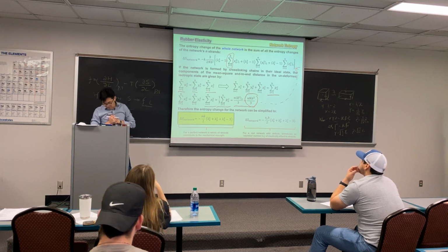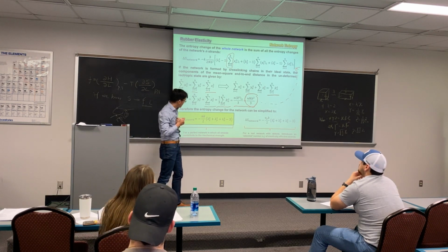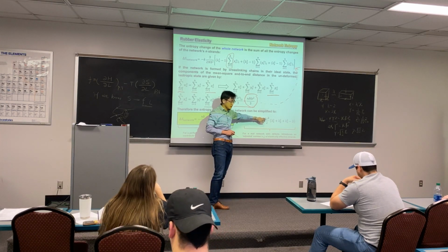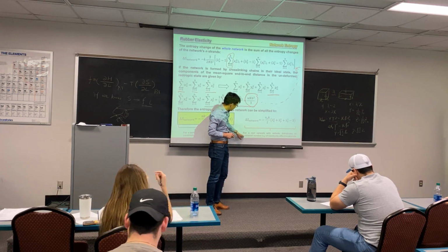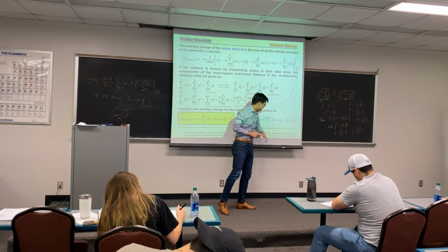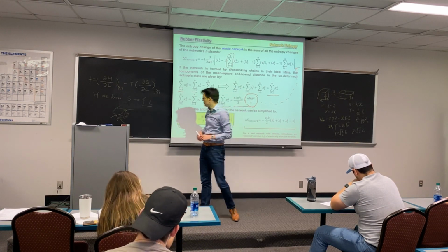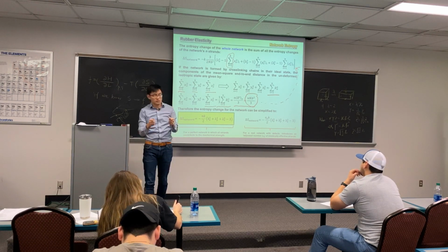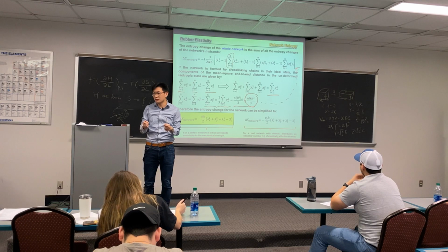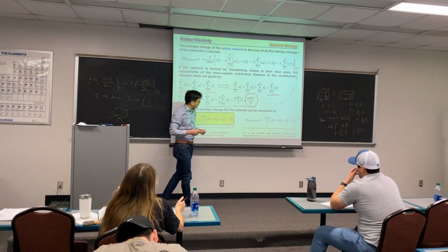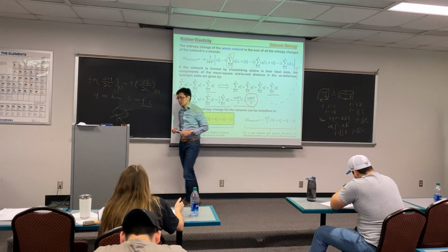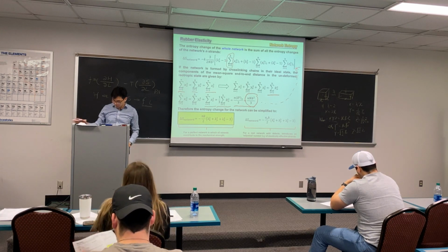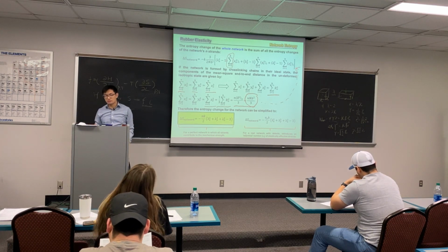you know exactly how much change there is in terms of entropy change. Of course, sometimes people would be more accurate to replace this N with a VE term. This is equivalent, called the adjusted number of elastically affected strands, because we don't have a way to count strands directly. We don't have a microscope to look at an elastomer to know the number of strands, but we can calculate this effective strands, and we will come back to what effective strands mean, because we can measure the modulus and come back to calculate this effective strands.